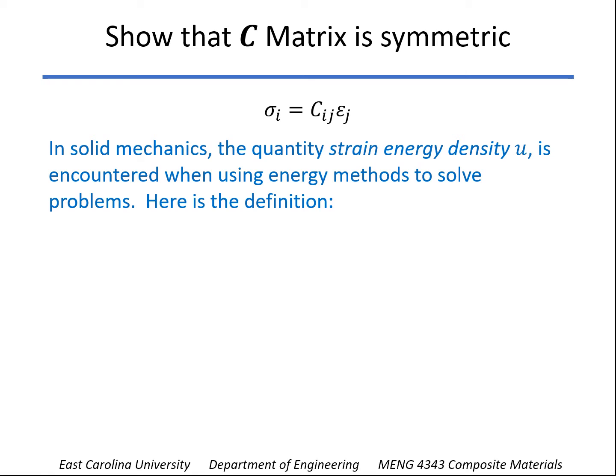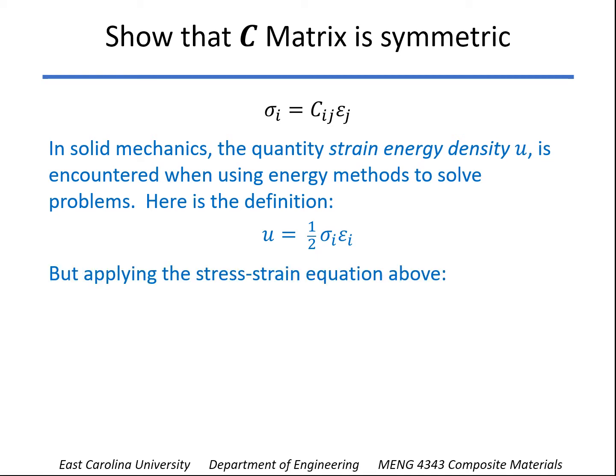And if a material has a linear response, then the area under the stress strain diagram would be triangular and would have the quantity shown here, 1/2 of stress times strain. And of course, all of the stresses and strains would contribute to the total strain energy. Okay, well, if you look at the stress-strain equation on the top of this page and we substitute that in for stress, you can see here's our expression then for the strain energy density.